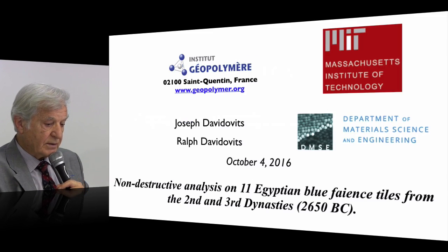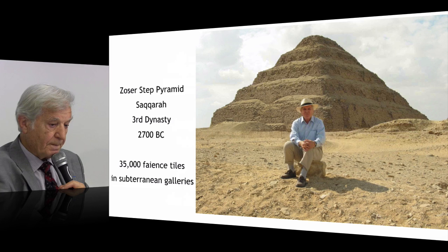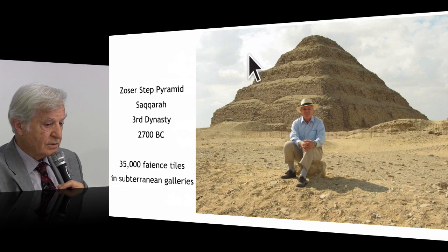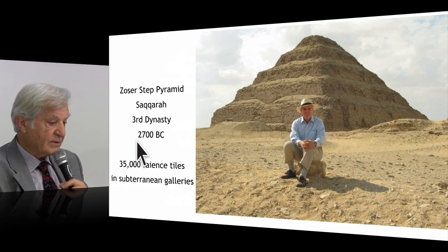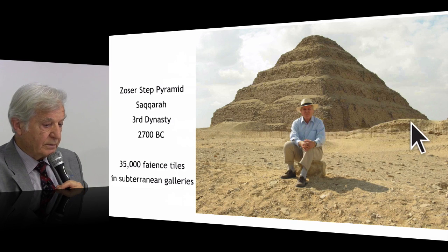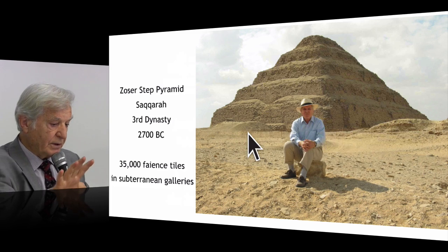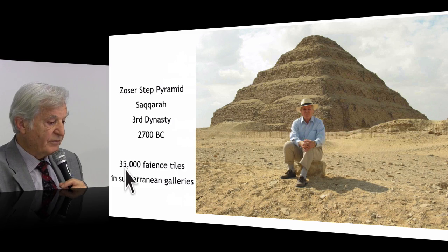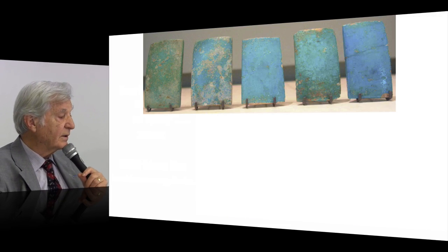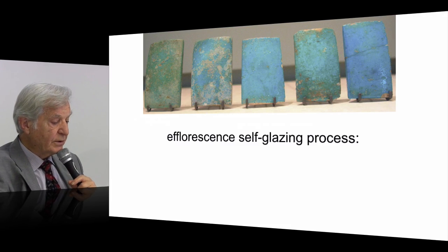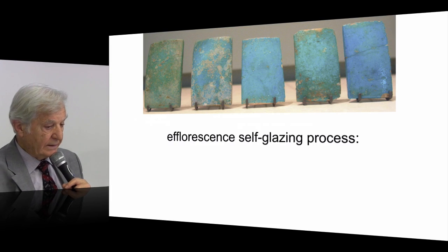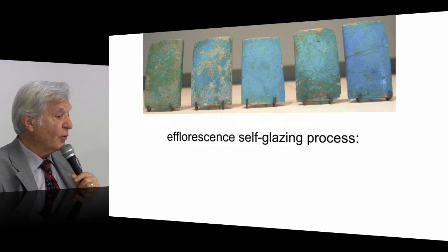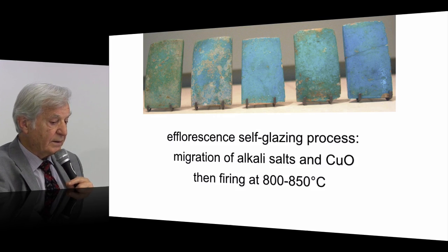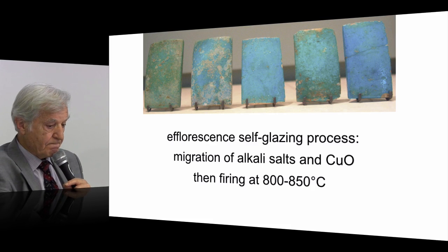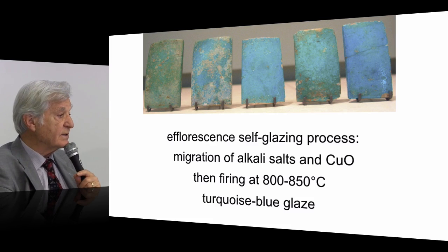We also presented this at a seminar at the MIT in October. What is it about? This is the first step pyramid in Egypt, 2700 BC, and in the subterranean galleries, they were adorned with more than 35,000 faience tiles that look like this, that you find in the museums. It is told that the glazing results from the efflorescence, the migration of salts, that are then fired at 850 degrees C,